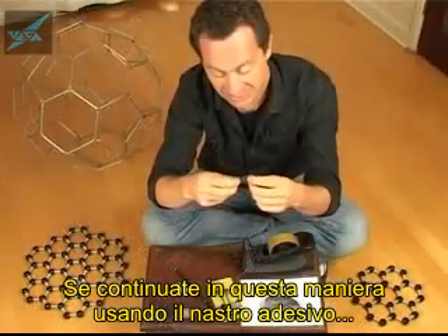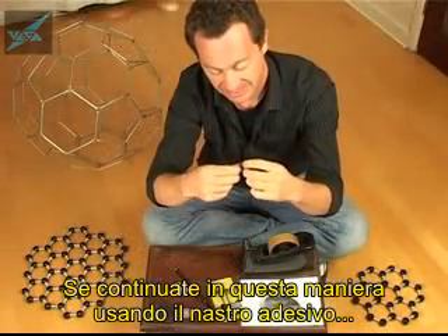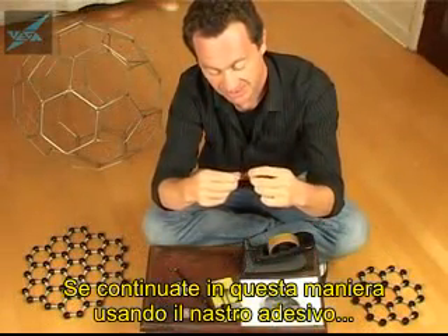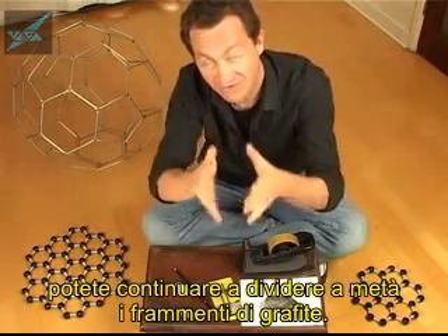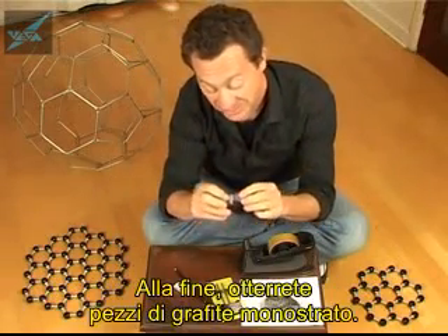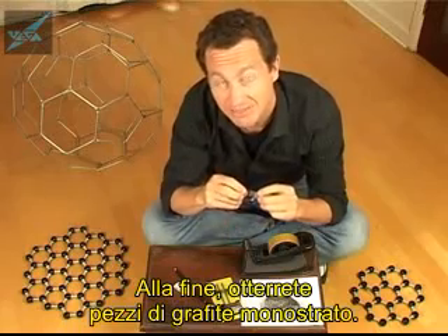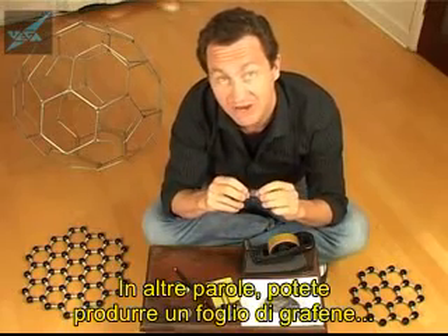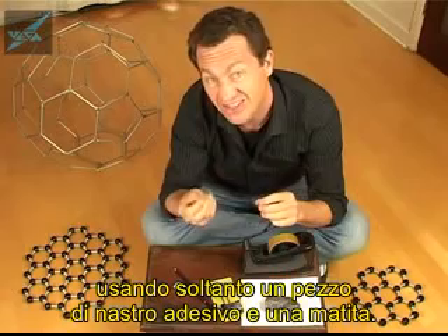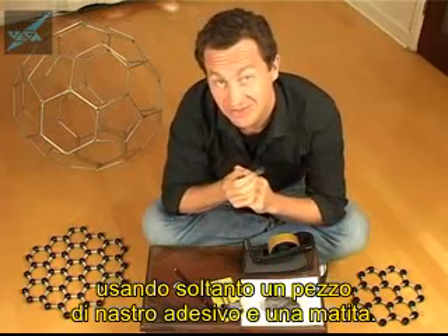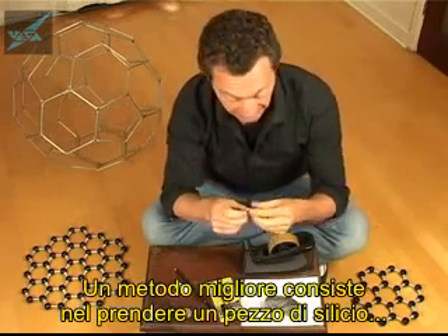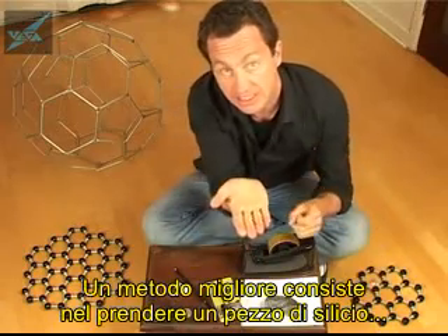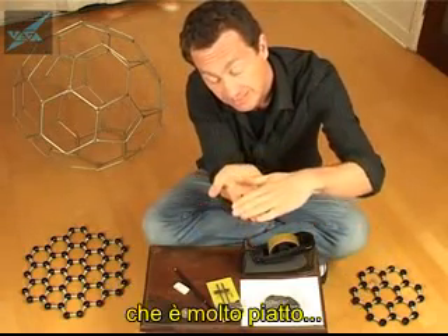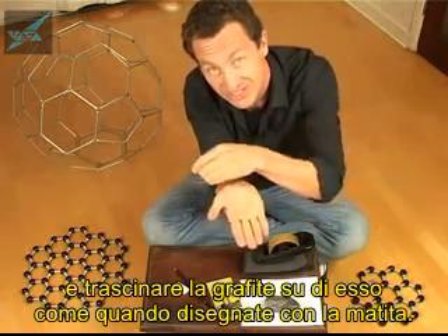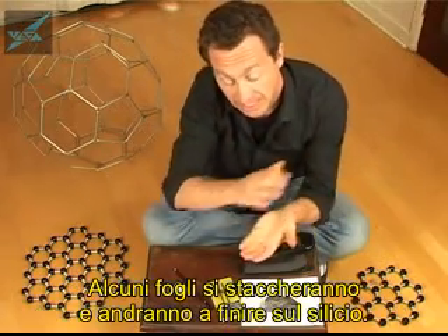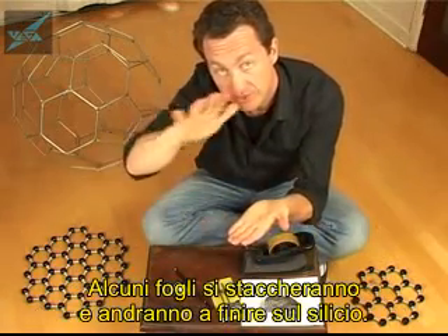And if we keep on doing that with these fragments, using the sticky tape, we can actually halve and halve and halve and halve these graphite fragments. And eventually you can make single layer pieces of graphite. In other words, you can make graphene sheets by nothing other than a piece of tape and a bit of pencil, basically. A better way of doing it is actually to get a piece of silicon, which is very, very flat, and draw the graphite across it, just like when you draw with a pencil. And sheets will come off onto the silicon.